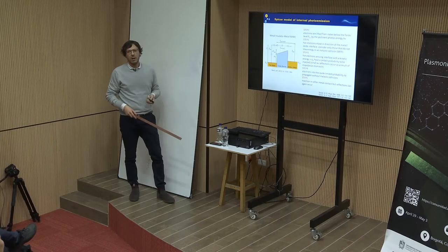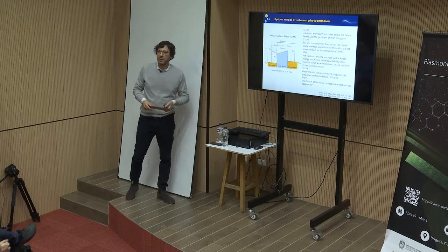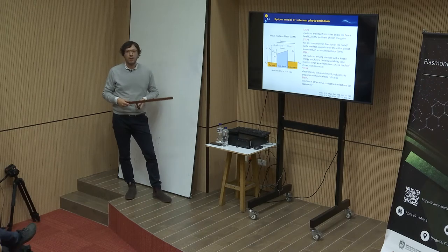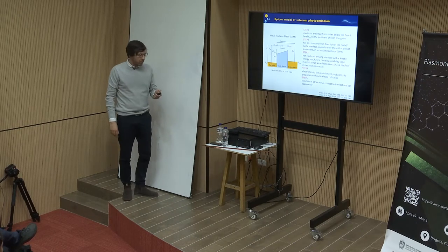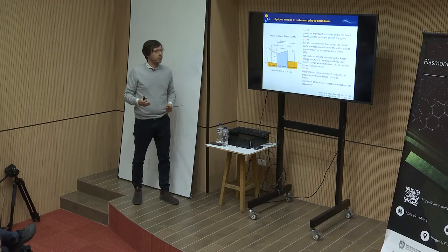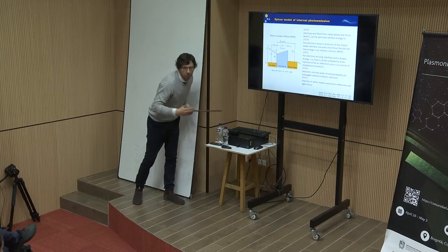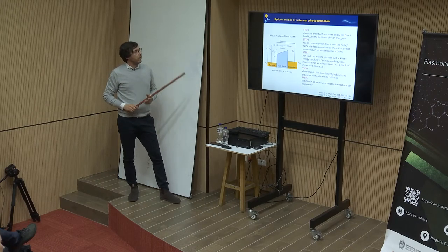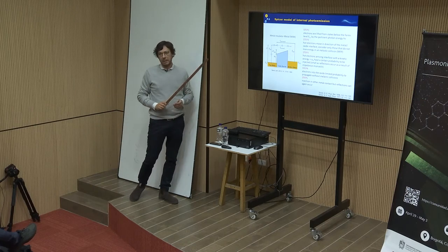Another interesting model to describe the efficiency of the process of hot electron injection is based on the Spicer model of internal photoemission. So the hot electron creation is basically internal photoemission of electrons. This model can be applied to metal semiconductors, where we have three steps to inject the electrons, or can be applied also to other types of photodetector schemes, let's say like a metal-insulator-metal stack.